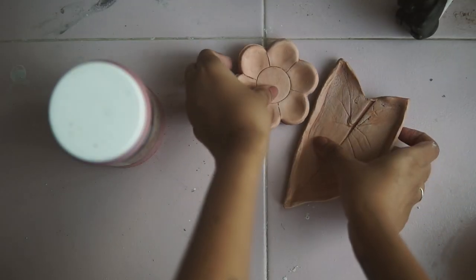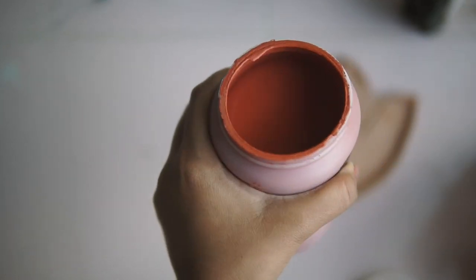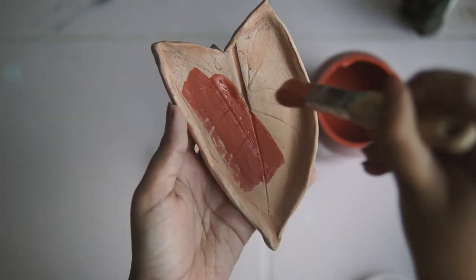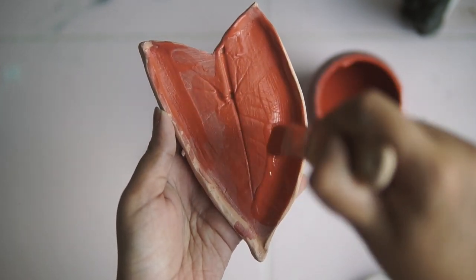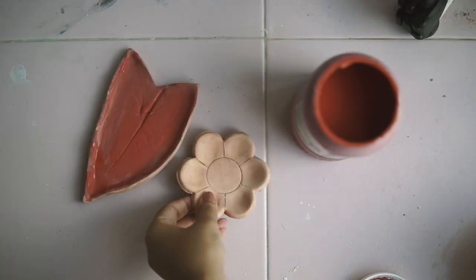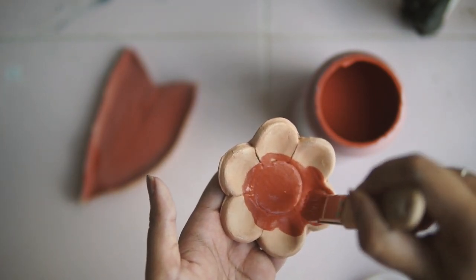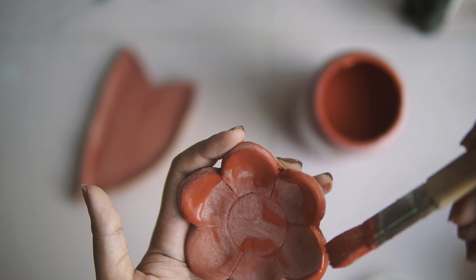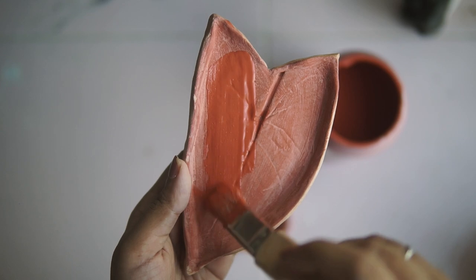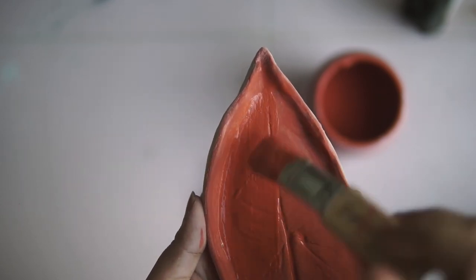I was very excited about this glaze — it's a really cool Japanese-style shino glaze. It looks red here but it won't be this red after firing. This glaze also looks different depending on how thick you apply it: one or two coats gives one look, more coats change the color. I went in with four or five coats. Each brush-on glaze dries pretty quickly — waiting three or four minutes between coats is usually enough. After finishing all the glazing and decorating, everything was ready for the second firing.